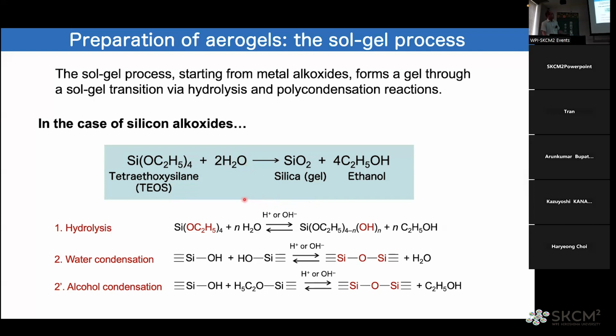And this overall reaction can be divided into two different types of reaction. One is hydrolysis, which converts the alkoxy group to hydroxy group, like this, with a reaction of water in the presence of acid or base catalyst. After that, this SiOH is called silanol group. Silanol groups are condensed like this reaction to form the silicon-oxygen-silicon bonds. So repeating this condensation process, then you can have the three-dimensional network, colloids, and then form the gel.